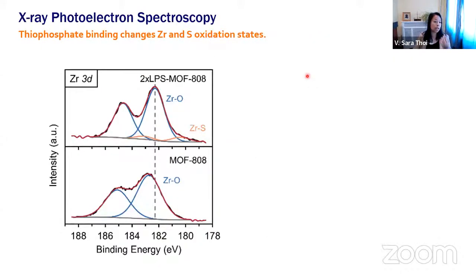Finally, we could also use X-ray photoelectron spectroscopy to show that these zirconium clusters are indeed affected by the thiophosphate functionalization. That's shown here. Here, we're using a different MOF, the same zirconium cluster, which has kind of one single local environment defined by these two peaks. If we add in the LPS, these two peaks shift significantly, and we can model that shift with these zirconium sulfur bonds that are now introduced into the system by our thiophosphate.